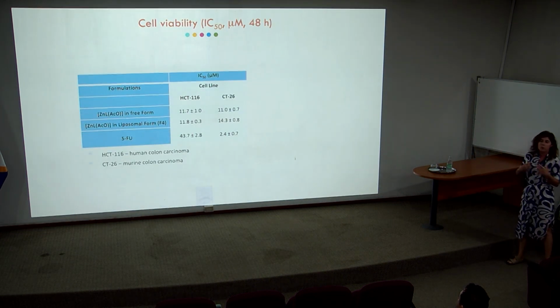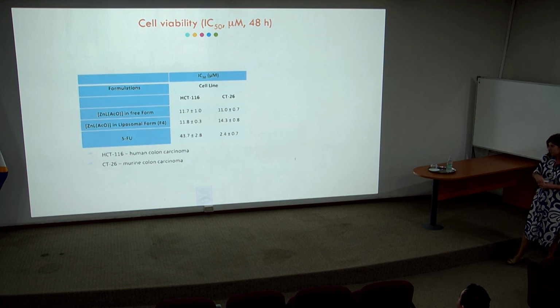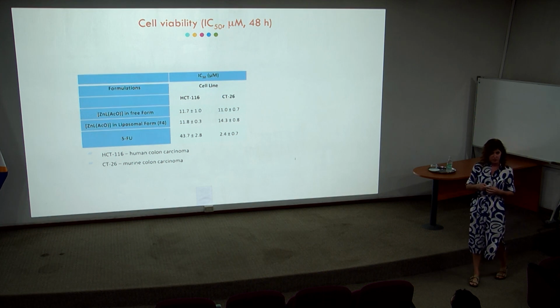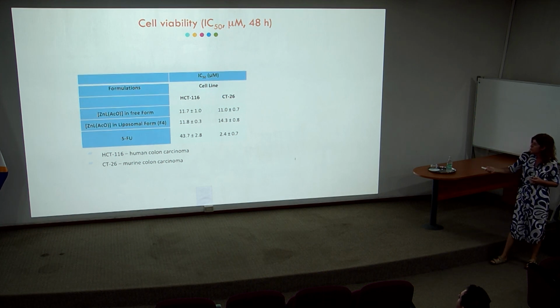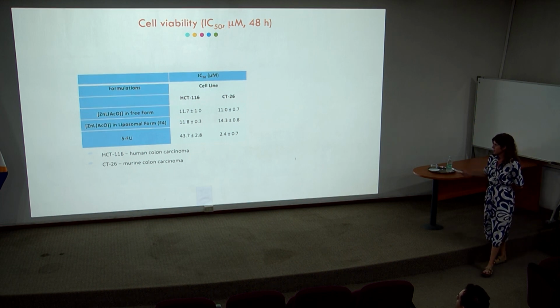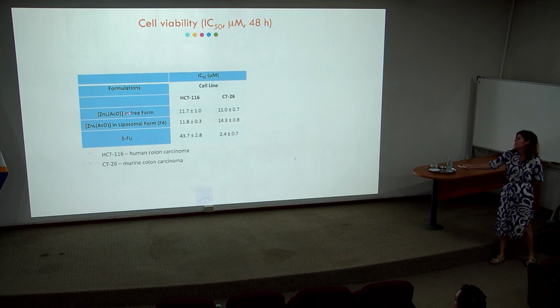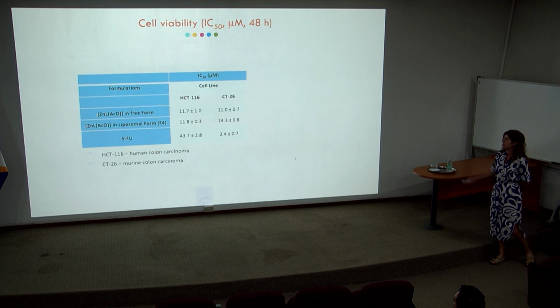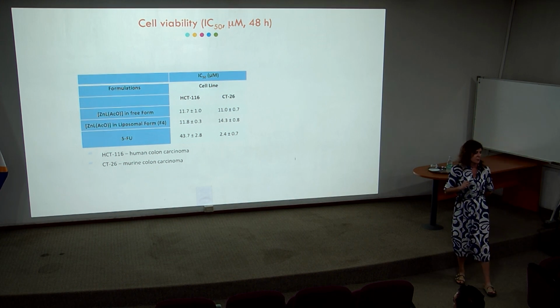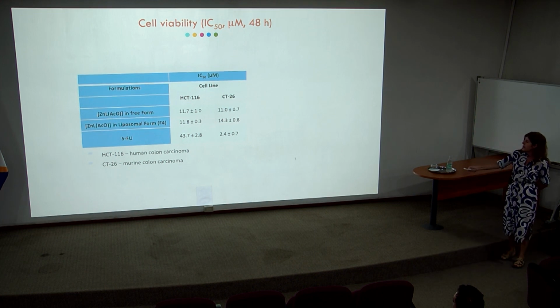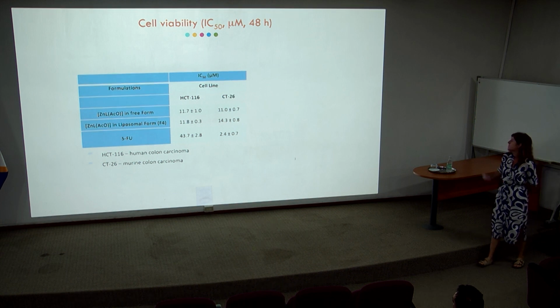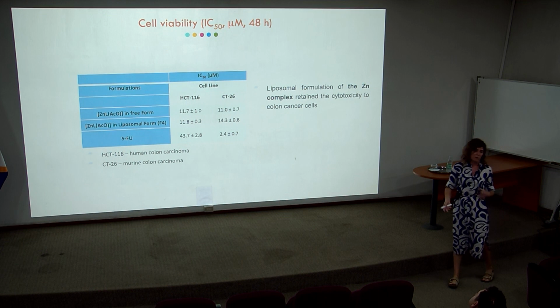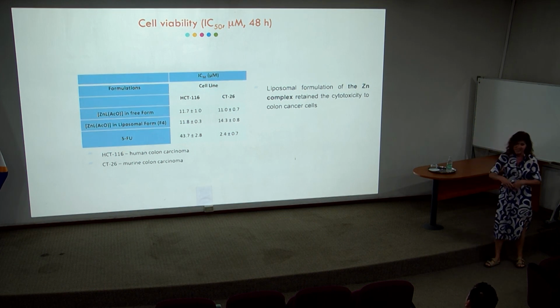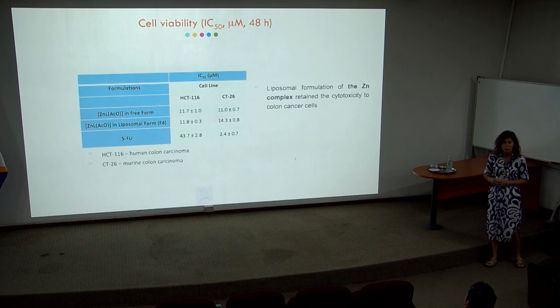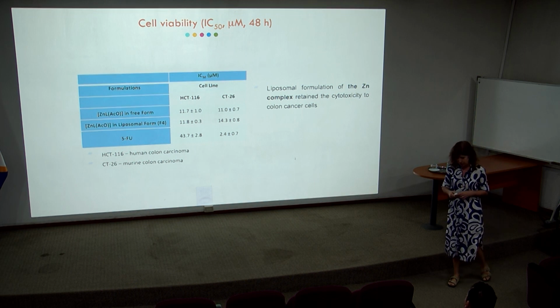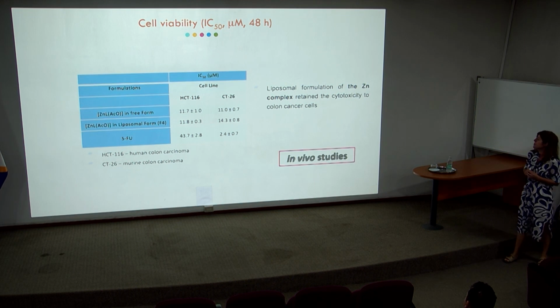What we did was to test if the liposomal formulation of the zinc complex was able to retain the cytotoxicity. And in fact, you can see here that for the human and for the murine colon cancer cells, the IC50 values of the complex in free form and in liposomal form were very similar. You have here the positive control that we used in this study, 5-fluorouracil, which also has a very low IC50 value in the murine colon cancer cell. And so this was a positive result, because sometimes after incorporation, if the compound is not easily released from the liposome, it has no cytotoxicity. So in this case, the result was what we were aiming for. So we proceeded to do in vivo studies.